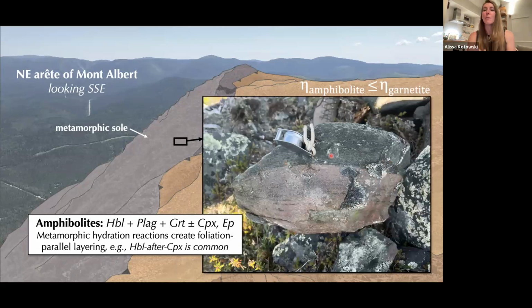This is also confirmed by this really nice example. Sometimes we see these garnetite layers. So this is all garnet here in this red color. And it's also just barely being pinched and boudinaged within this amphibole-rich matrix. So we're getting a sense from looking at other minerals that we have good quantitative and qualitative indicators for in terms of their rheology, that these amphibolites are actually behaving quite strong.